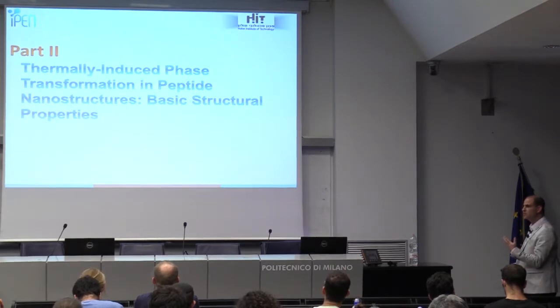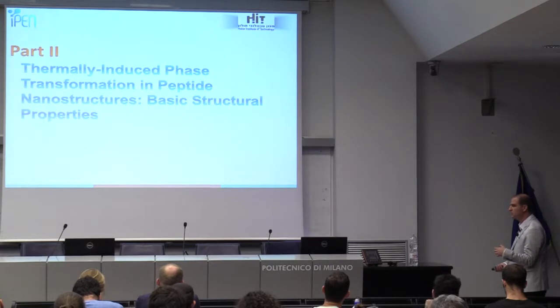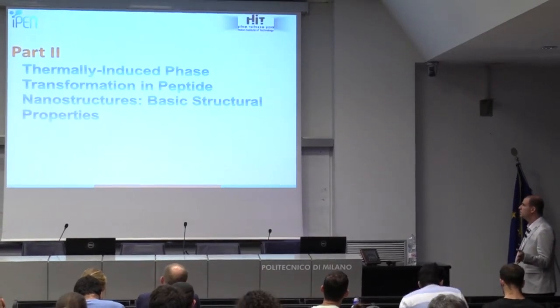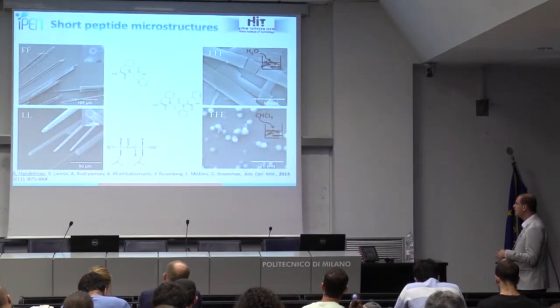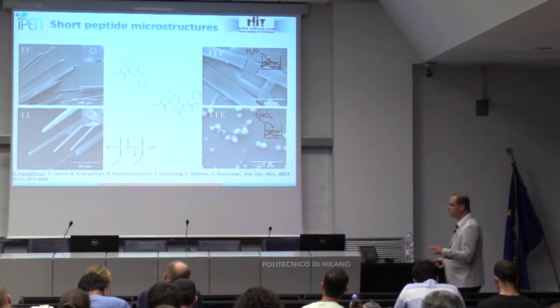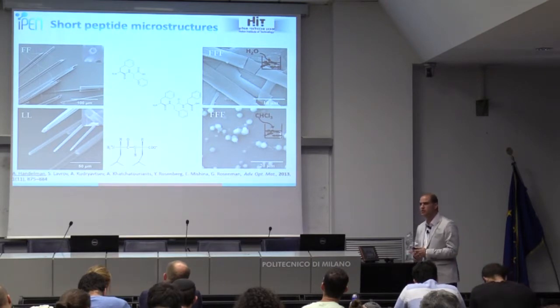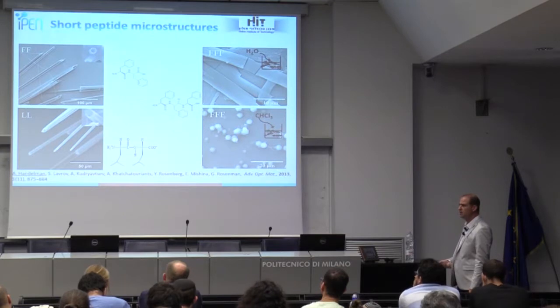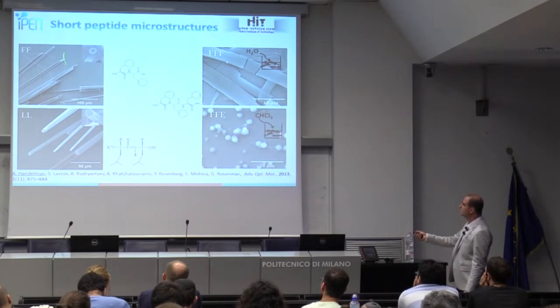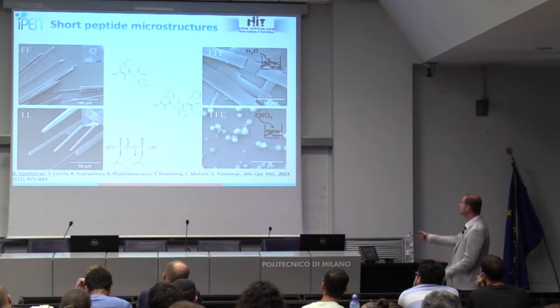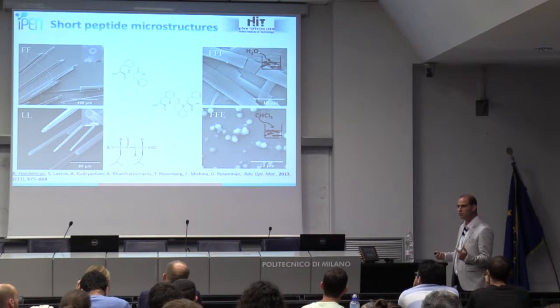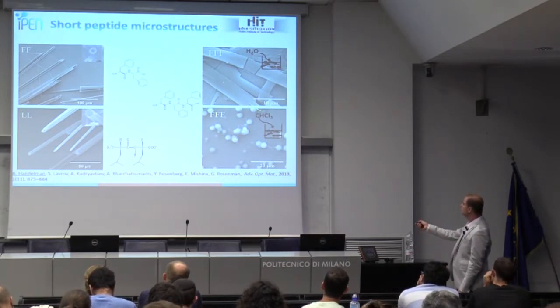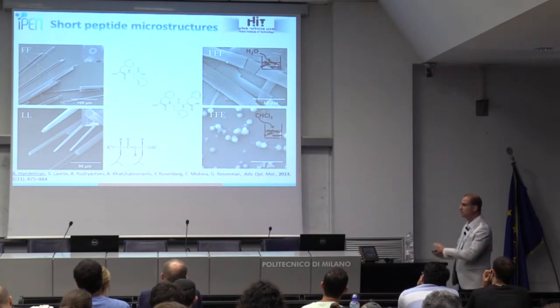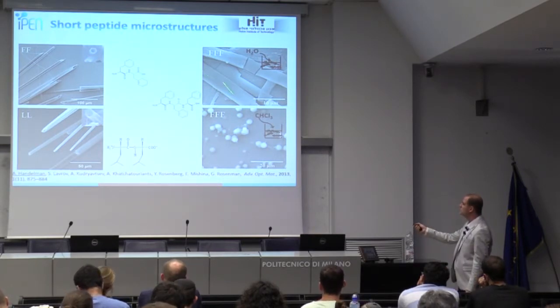Now I'll show you a very interesting characteristic of this kind of peptides, which we discovered about 10 years ago, maybe even less, which we call thermally induced phase transformation. This is a photo of all kinds of peptide microstructures that we develop in the lab. For example, if we take the diphenylalanine, which is composed of two phenylalanine amino acids, we get very long microtubes with hexagonal cross sections. If we add another phenylalanine, so we get the triphenylalanine, we get microplates. It's a completely different morphology, as you can see here.